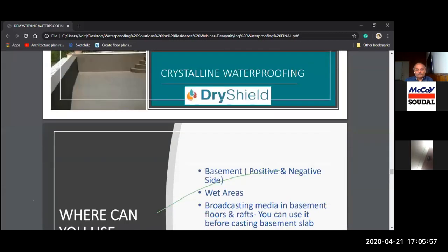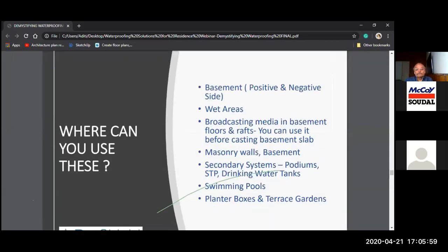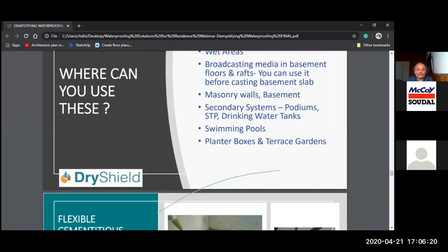So it's, again, planter boxes, terrace gardens. I've used this product extensively there as my basic coating. And after this, any other product is applied. Normally I use it when the surface is still green, immediately after the casting is done. So within 7 to 8 days of the casting, we use it.